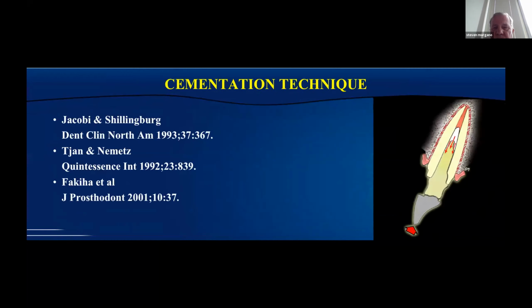So probably more important than the cement that we use is our cementation technique. So if we look at the artwork all the way to the right, if I put cement only on the post and just place the post into the post preparation, as soon as the liquid cement touches the opening of the post preparation, I'm going to trap air. That air has no place to go except through the cement film. So if we look at the study to the left here by Jacobi and Shillingburg, they cemented posts using clear plastic analogs in vitro. And they just put it on the post only. When they cemented the post, they could see the cement film. And it was about a third air. Then they entered the cement into the post preparation first using a Lentulo spiral, then covered the post with cement, and they didn't have air voids.